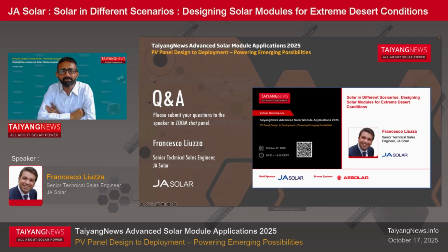All our desert models and also TOPCon models are now based on double glass versions, and we also believe that in different conditions, even in high temperature conditions, double glass with a specific encapsulant developed for different scenarios is the best solution, also to keep safe and confine any kind of losses on TOPCon cells. So all our series are based on double glass versions. Even though we recently released lightweight versions with backsheet on the rear side, with a specific material that can offer lower permeability to moisture and a safe encapsulation pack, even on monofacial. But our first choice and our strategy is based on double glass models, even for deserts.